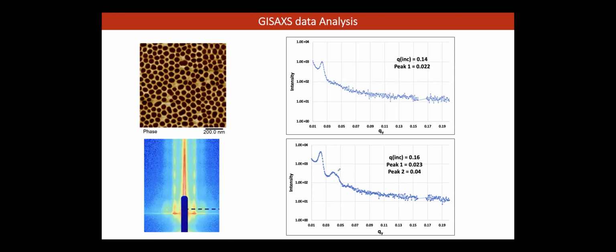In fact, this tells you that inside the film, it is more homogeneous, uniform. And the reason you would get a second order peak is because of the longer range correlation in plane of the structure. So we learned something right away, that it's actually better than it looks at the surface. So now what's the reason for that?